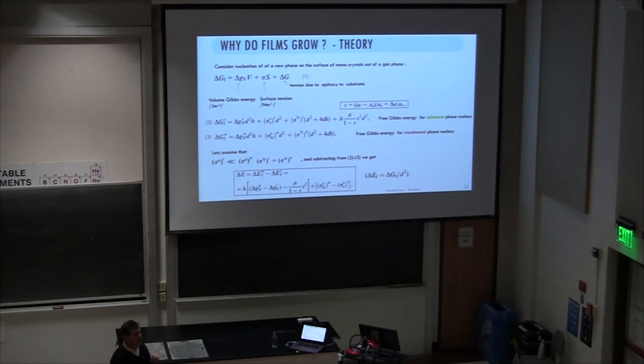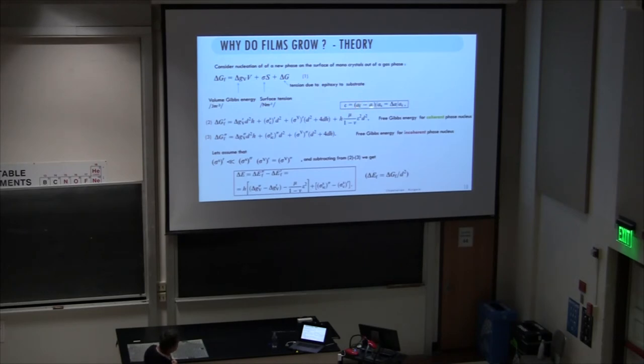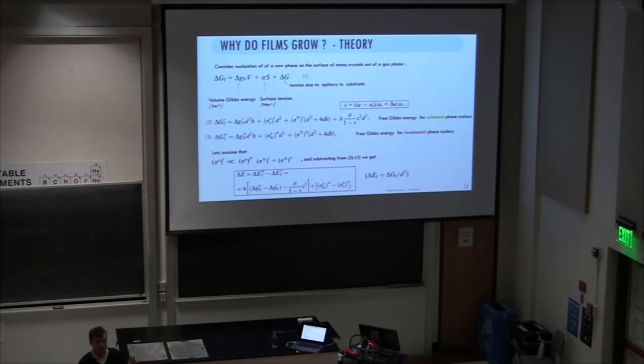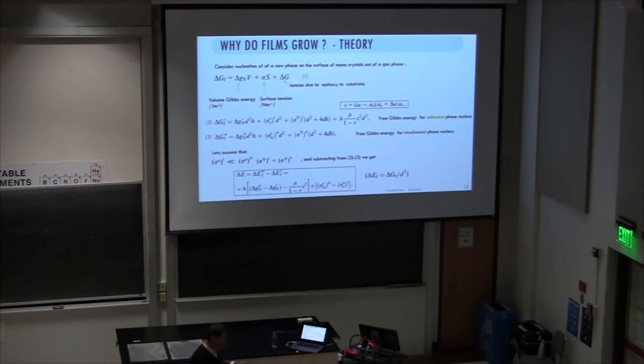The strain — or lattice mismatch — is ε = (a_film − a_substrate) / a_substrate. That's your epsilon, which enters the Gibbs energy formula. It's the mismatch between the new nucleus and the substrate lattice parameter. I'd like you to understand that once you deposit something on the surface, all possible new phases will start developing given the thermodynamic conditions. There is no guarantee that what you grow is the material you want — everything is on the table.